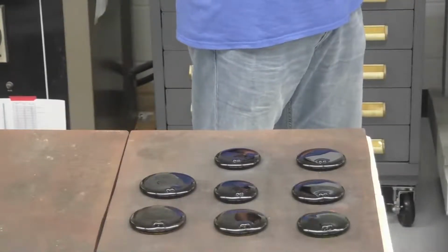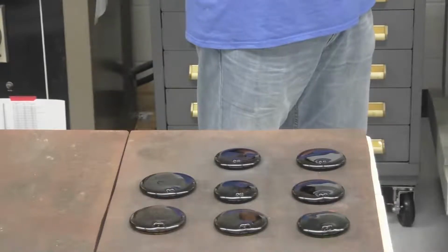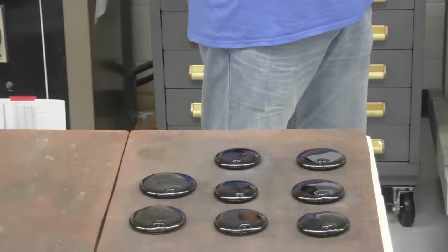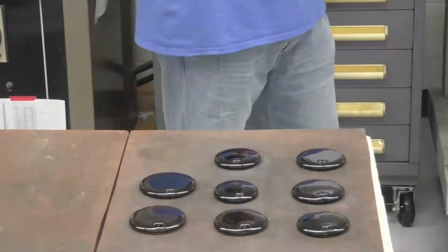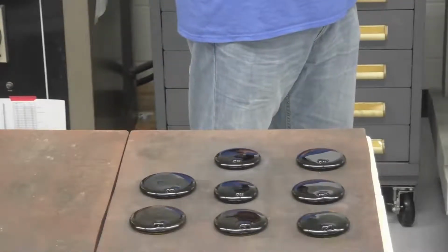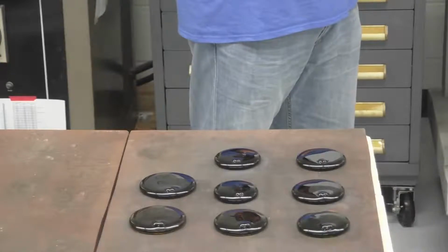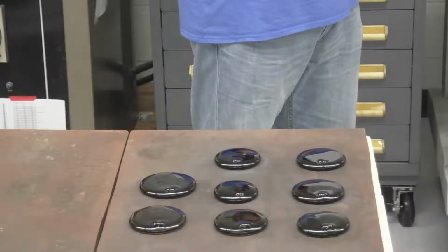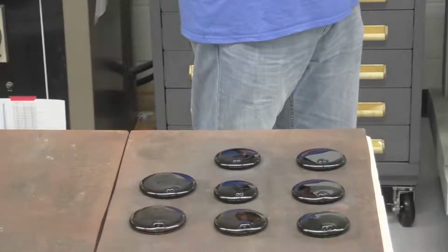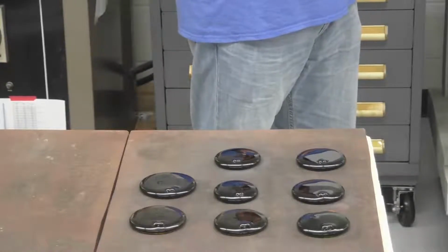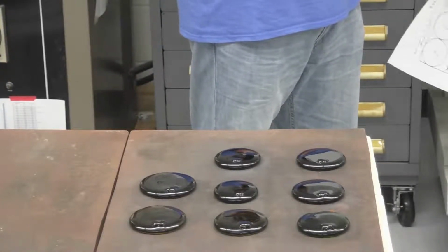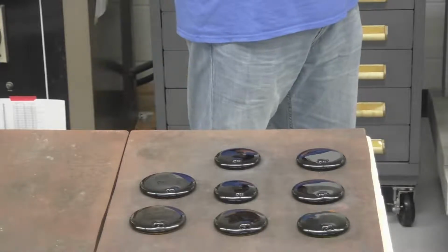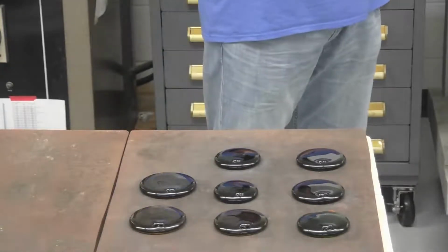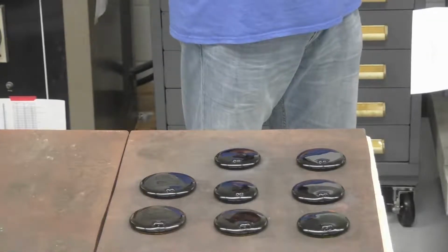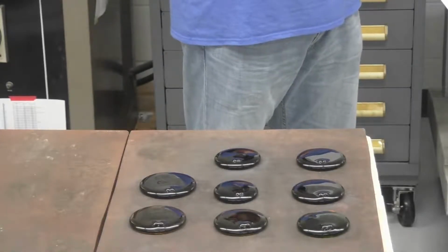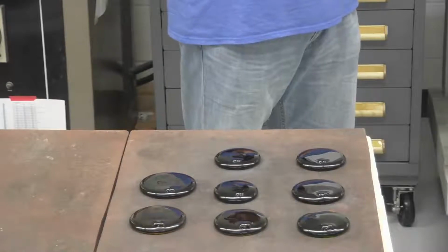So we were ramping between 6 and 11, almost there, up to 928. And then it sort of plateaus off and approaches that asymptote of 1150 more slowly. So then it probably reached that after another 4 or 5 hours. The last 100 degrees, it just inches up to it. But you normally want it to sit at temperature for long enough to get all the bubbles to pop. You saw in my preliminary discussion, we're creating carbon dioxide in this process. Well, that makes bubbles in the glass. So the process of letting it stay at temperature is called fining the glass.